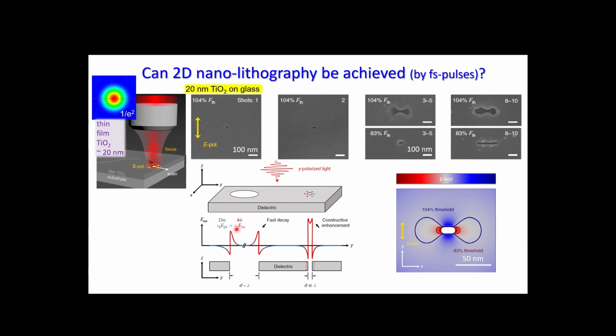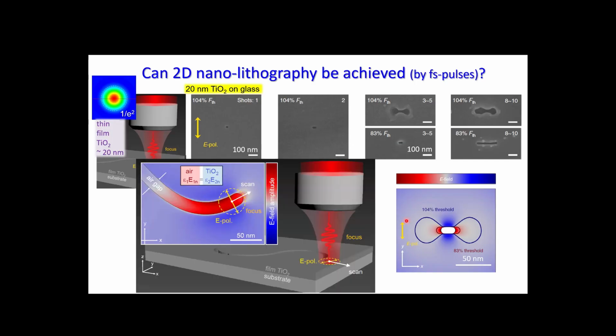And permittivity is refractive index squared. So the ratio between the refractive indexes of titania and air is 2.5, and the square of this is 6. And intensity is the electrical field squared. So intensity is almost 40 times higher inside the groove. And this is what you see, it's not a cartoon, it's really modeling. So the focal spot is actually huge. It's around 1 micrometer in focus on this side. And this shows how light intensity is distributed in the groove,